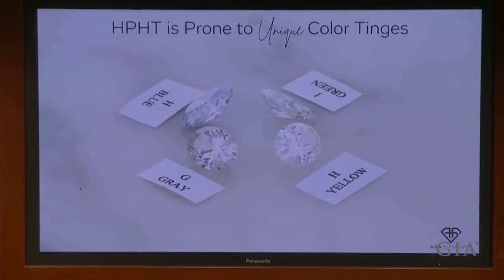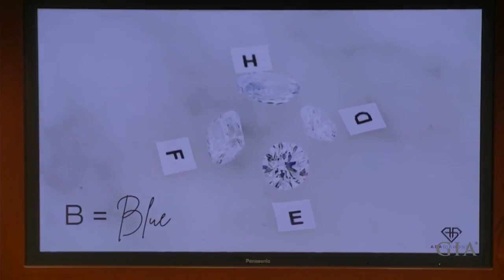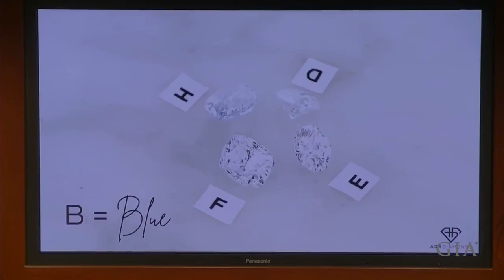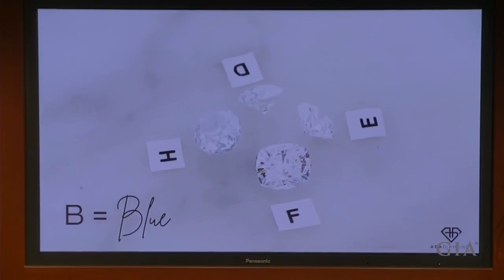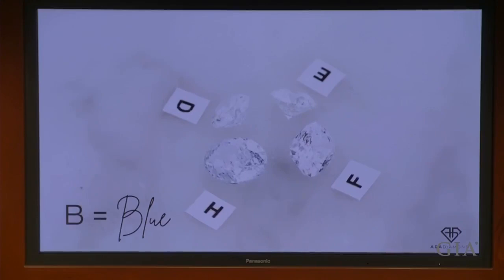The first of BGY is B for blue. Blue tinge in HPHT is very, very common — it is due to trace boron that is added during the growth process to compensate for present nitrogen. Measurable levels of boron is known as Type 2b, and about 75% of HPHT diamonds that GIA sees are considered Type 2b. Type 2b diamonds are more likely to have a blue tinge but may not necessarily have one. Type 2b natural diamonds are exceptionally rare — they make up 0.1% of the gemstone market and fetch much higher prices per carat than blue tinge laboratory-grown diamonds. When we talk about blue tinge from boron defects, that does not mean you personally should like or dislike a blue tinge — but it is considered a crystal defect.